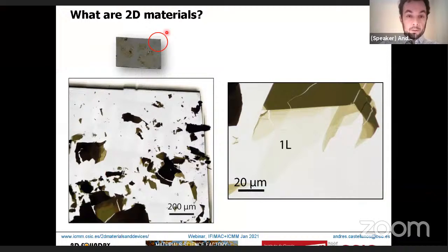Okay, so in this corner here, if we zoom in, you will get this image here. So this is this corner here, and you can see how we have different flakes. This is a transmission mode optical microscopy image. So black means very opaque, and you can see how you have flakes that are very opaque and flakes that are more and even more transparent because they are thinner and thinner. And eventually there are flakes like this one here that is just one single layer. This is a single layer of molybdenum disulfide transferred on polydimethylsiloxane. And we can find it just with the optical microscope.